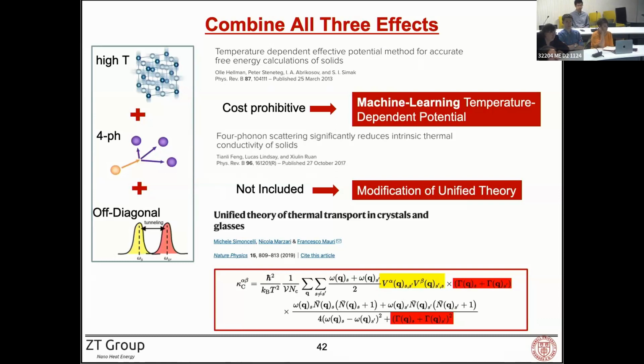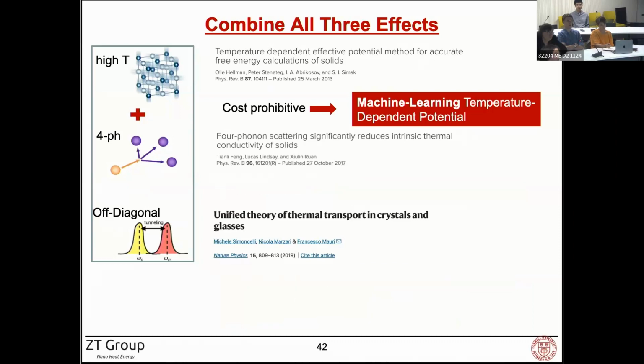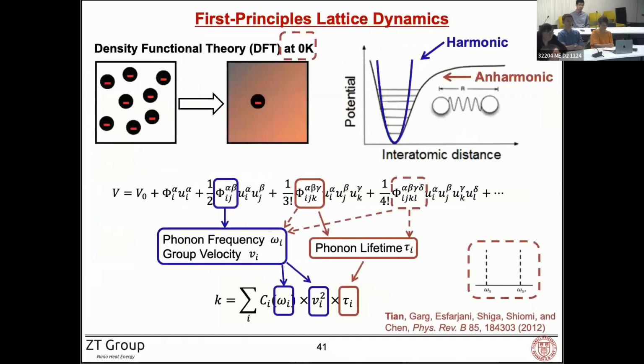Okay. So what I mean is, in addition to just having this temperature potential, and then we calculate the force constants, and we come back to the equation here. For example, in our case, we can easily fit up to, say, 6th order or even higher order potential. But to consider the contributions of the 4th order, we cannot come back here. We fit the forces and the displacements to extract the 3rd order and the 4th order force constants, and then we use the Boltzmann transport equation to calculate the thermal conductivity.